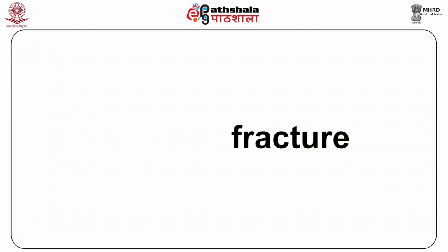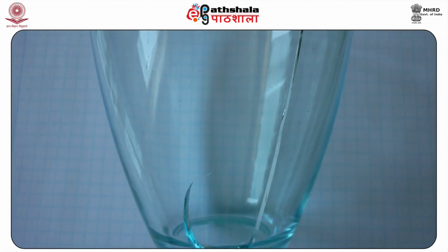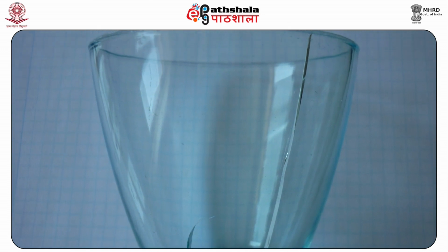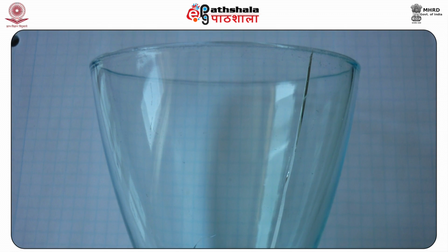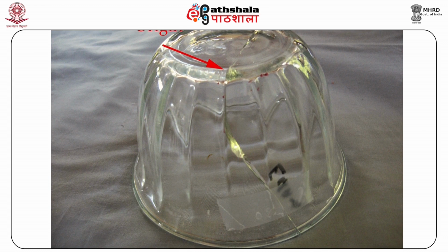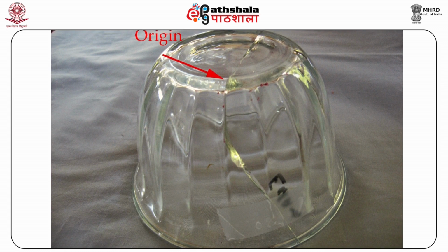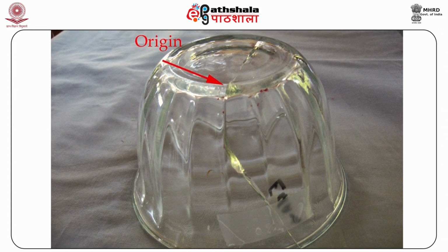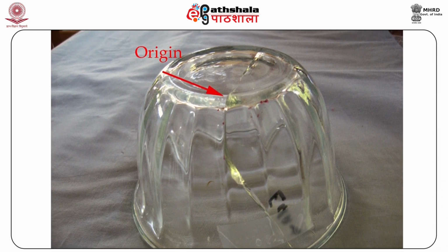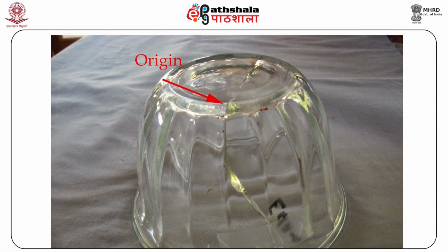Thermal fracture. If very hot liquids are poured in cold glass or very cold liquid is poured into hot glass, a thermal shock is produced leading to fractures. These occur in the bottom of the container around the circumference with no or very rare surface markings, resulting in fracture along the long axis of the container.